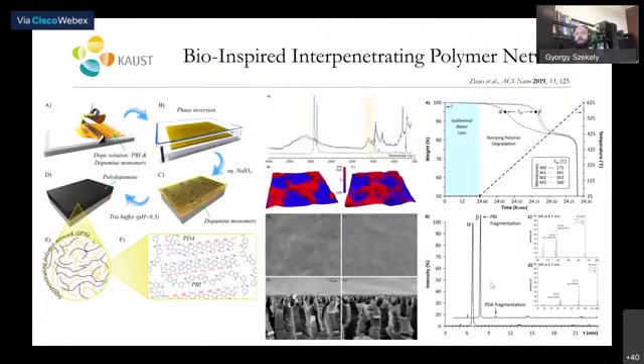Another way of gaining control over the performance of the membranes is by using bioinspired interpenetrating polymer networks. In this idea, again, we wanted to break conventions and move away from the traditional cross-linking of membranes, and we explored growing an IPN, an interpenetrating polymer network, within a polymer framework. We hypothesized that this will result in a stable membrane that we can use in harsh environments.